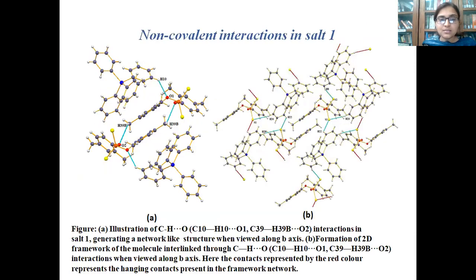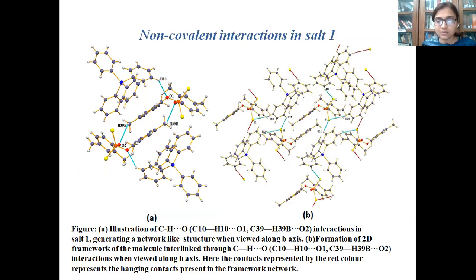The next slide presents the various non-covalent interactions present in Salt-1. Figure A represents the C-H···O interactions present in Salt-1. The two monomer units of Salt-1 are interconnected through two C-H···O interactions — C10-H10-O1 and C39-H39B-O2 — resulting in the formation of a network-like structure. The various monomer moieties connected through these C-H···O interactions form a network-like structure which, when viewed along the B-axis, shows the pattern represented in Figure B.